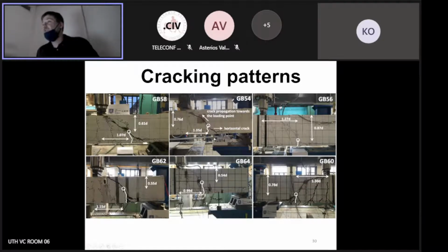But what was interesting, what I found there, is that actually this initiation point is a function of the overall or effective depth of the element. And the higher the element, the taller the element, this initiation point was actually placed lower, which really affected the inclination of that shear crack.